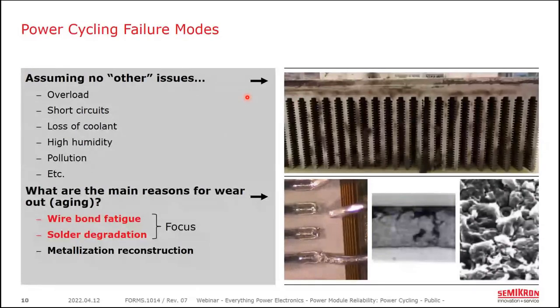But if you can manage to avoid all these things and get to the end of life, that right side of the bathtub curve we showed earlier, then the module will eventually fail, and the primary failure modes are shown here: wire bond fatigue, solder degradation, and to a lesser extent, metallization reconstruction.